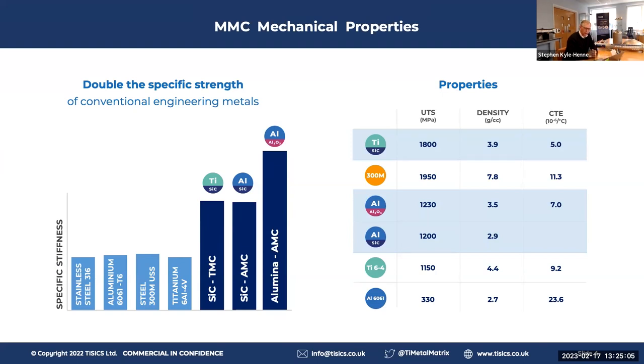And that's important when you think that your temperature range could be plus 50 degrees C to minus 250 degrees C. It's quite a change there in properties. And this is where our material has unique capabilities for this application.